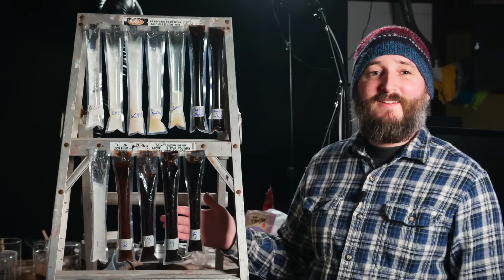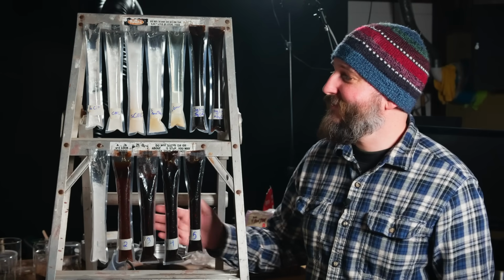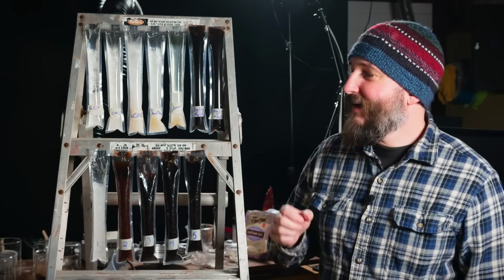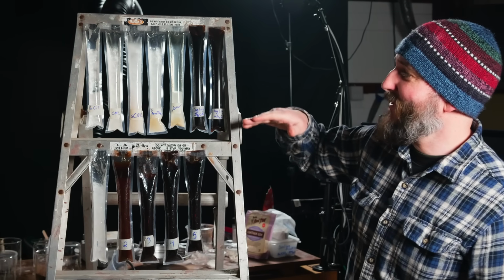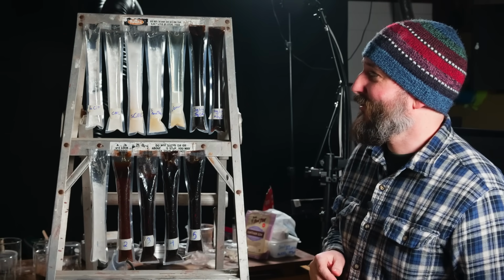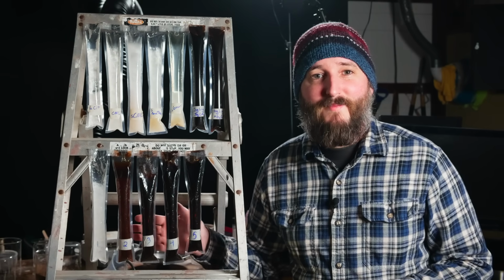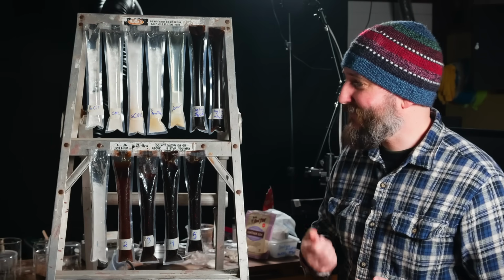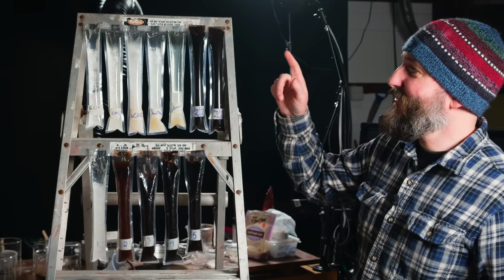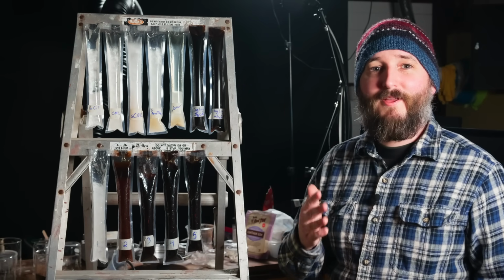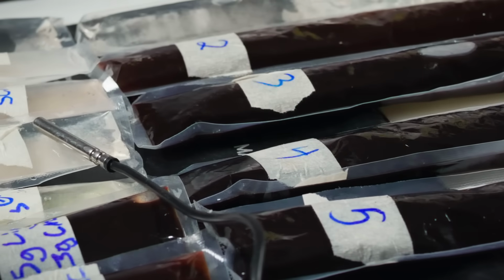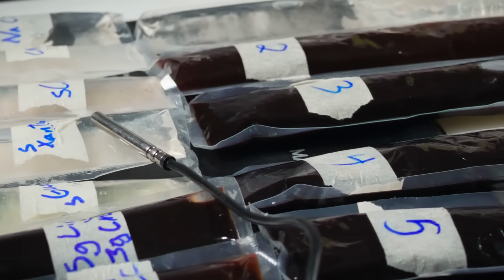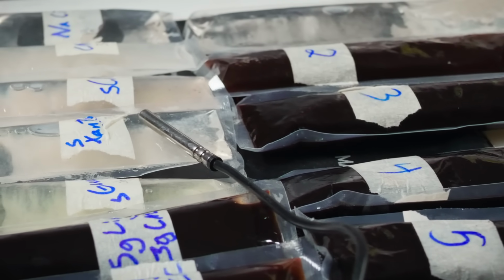So now let's move on to test the stability of all these samples under thermal cycling. And to do that, because they have dehomogenized many of them in this vertical position, I'll go ahead and remelt all of these samples, mix them around so that we have an even distribution of ingredients throughout the tube, because that series of tests will be conducted with all these tubes lying on their side.